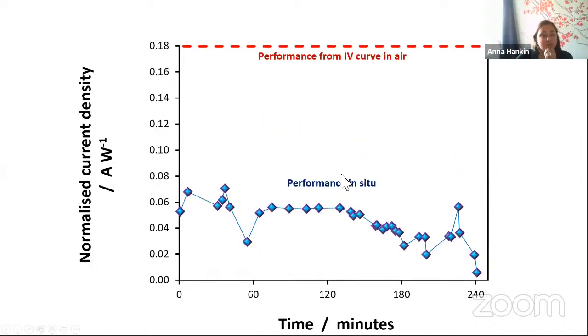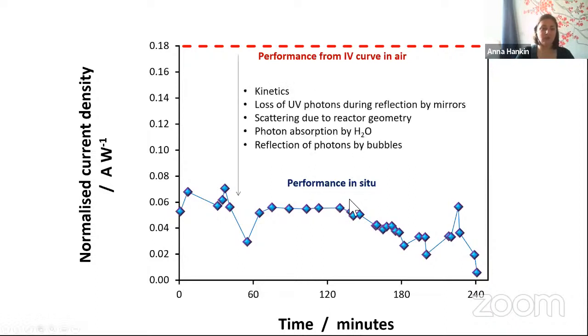But what was definitely very apparent is that if you compare the performance of the triple junction solar cells in air, without any coupling to electrochemical processes, and performance in situ, you can see this huge drop. And it's predictable because you have loss in intensity, photon absorption by water, reflection of incoming photons by bubbles, kinetic losses, i.e. the fact that you need 1.23 volts to drive the reaction, and loss of photons due to reflection by mirrors.